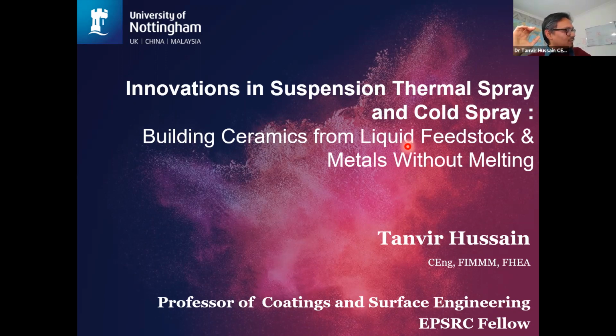I've got a couple of samples in front of me. This one is a high pressure turbine blade from a Trent 900 engine. It's an air cooled turbine blade, nickel-based superalloys, and it has got a very fine white coating on top. That white coating is as thin as my hair, roughly 100 micron, and it drops the temperature by 100 degrees Celsius. That's equivalent to taking an ice cube out of the freezer, putting it in the oven, cranking the heat up to 200 degrees Celsius, and you expect it not to melt. That's what we're doing, and these coatings are essential in our engine operation.